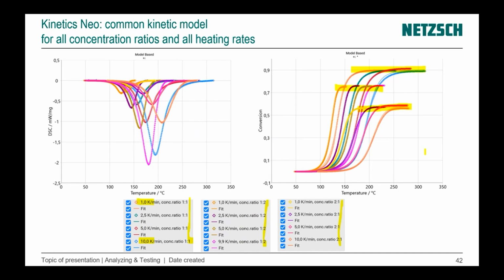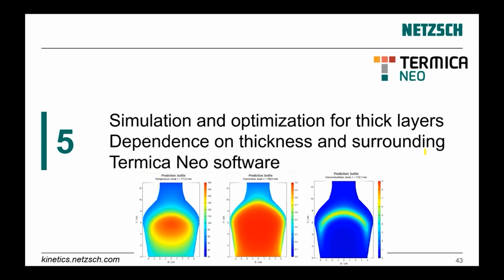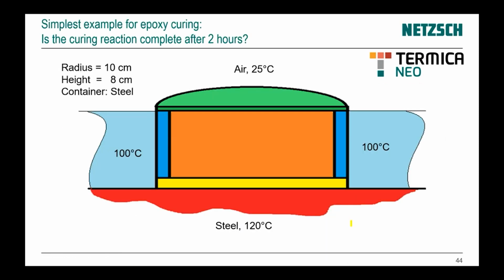So we can see that our model can describe everything, the heat flow, and it can also describe the enthalpy of reaction. And the final part is our Termica software, which can make a simulation of the peak volumes, including the production of energy and some overheating for the peak volume somewhere in the middle. For example, the first picture shows temperature, the second shows degree of conversion, and the last one shows the rate of conversion.